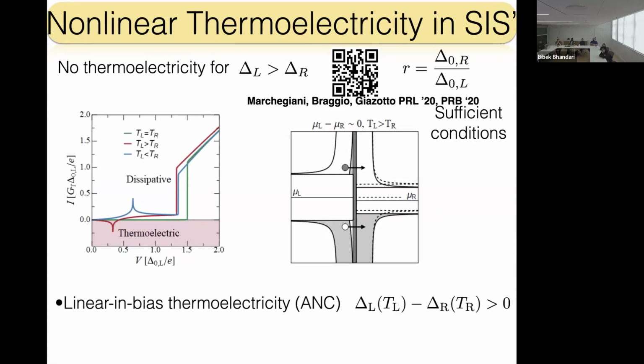Now, things become weirder if you consider an asymmetric system. Because look what happens. You do exactly the same argument, but you know now the following thing. When this reduces, okay, you see that the density of states reduces. So now when you put the chemical potential in this direction, you expect that the current goes in this direction for a quasi-particle. And now you see that instead, due to the fact that the density of states is monotonically decreasing with the energy, when they go down, this density of states goes down. So in a certain sense, what happens is that the quasi-particle states reduce and the quasi-hole states increase. So you put the chemical potential in this direction, you get the current going against you. This is a thermoelectric effect, essentially.